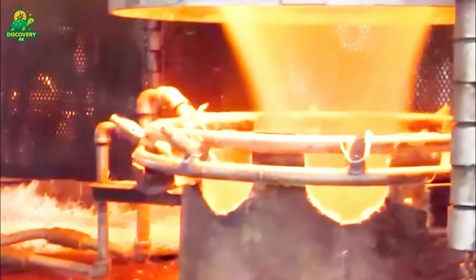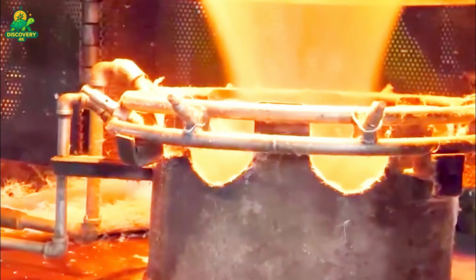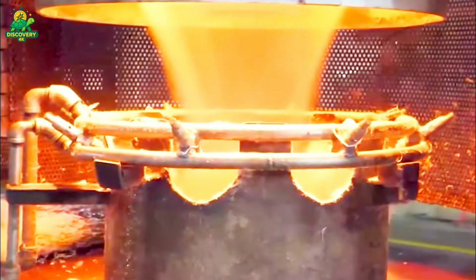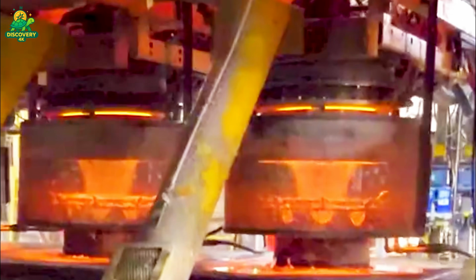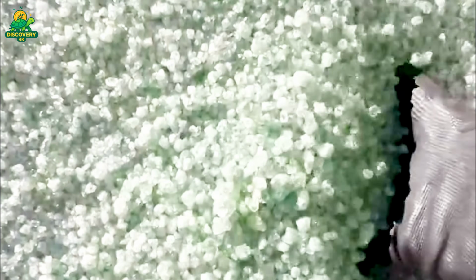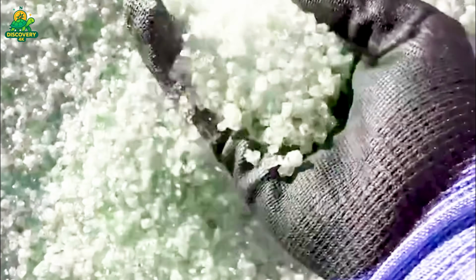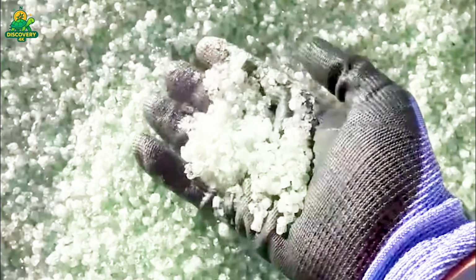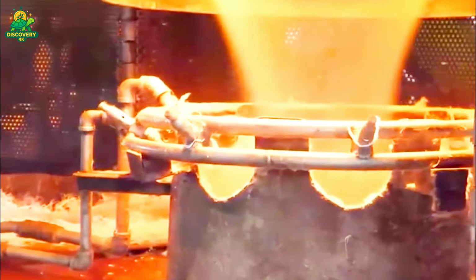The firing stage is where these lifeless chunks of glass and clay turn into something you'd actually want on your kitchen wall. The tiles are loaded into tunnel kilns, basically giant ovens the length of a city bus. Slowly, they move through zones that get hotter and hotter until the temperature reaches between 1,500 degrees and 2,200 degrees Fahrenheit, about 800 to 1,200 degrees Celsius. At these temperatures, the glass particles soften and fuse together into a solid mass.